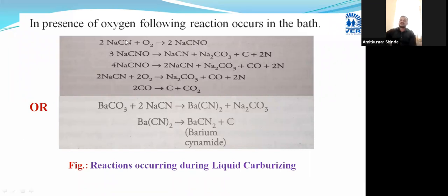NaCN, sodium cyanide, combines with oxygen and gives you sodium cyanate. Again, the sodium cyanate will decompose and form sodium cyanide, sodium carbonate, and carbon, and nitrogen is formed.